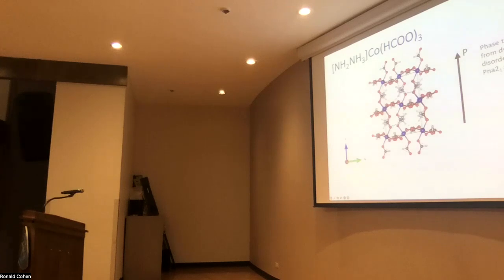All right, so here is hydrazinium cobalt formate. We have been working on this material for quite a while. It's a hybrid organic-inorganic perovskite. This material is dynamically disordered at high temperature. It's in the Pnma space group, and then at a temperature of 343 Kelvin, it undergoes a phase transition into the polar Pna21 space group. Here the direction of the polarization is along the c-axis, and we were interested to study piezoelectricity in this material, and for that we used density functional theory computations.